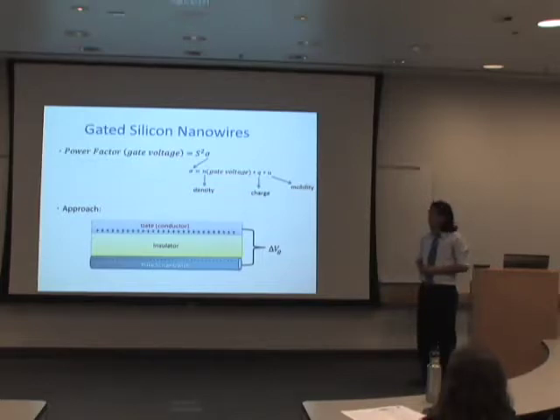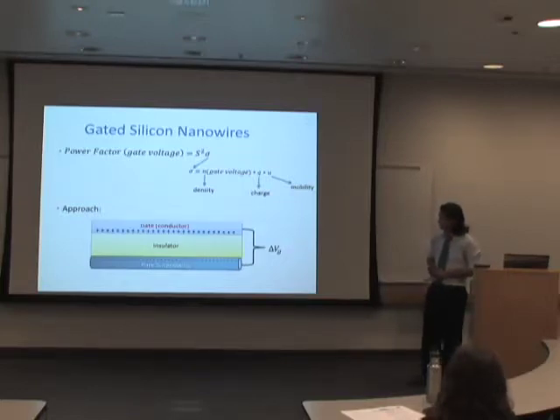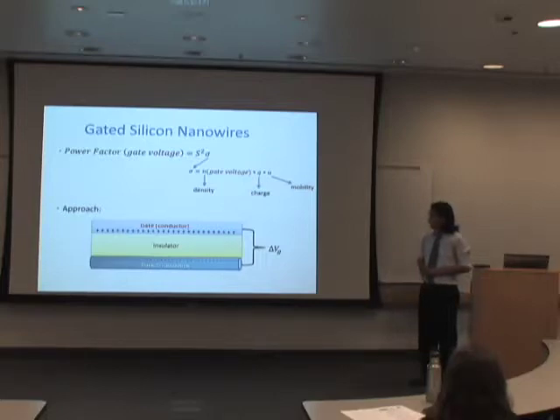So now power factor becomes a function of the gate voltage, not a function of how many impurities we put in there. This way we can understand how power factor changes as we add different amounts of carriers into this silicon nanowire. Our goal is to understand how power factor changes with different gate voltages and find the point where it peaks for optimizing the efficiency.